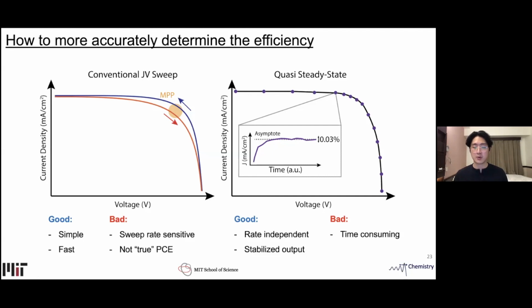So a typical measurement takes about 30 minutes compared to less than a minute for a conventional JV sweep, which means that an unstable device will not survive this more robust measurement and can degrade during testing.